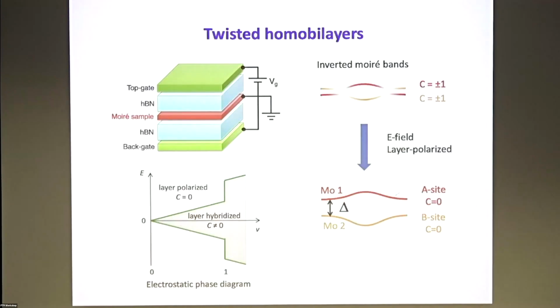So this is a typical device structure that we look at. Sometimes a bit more complicated, but this is sort of the idea. This is the twisted bilayer sample sandwiched between boron nitride, which is a very good gate dielectric. And then the top and the bottom are usually graphite gates, pure few-layer graphite gates. And because we have two gates here, we can tune independently the density of electrons in the system, as well as the vertical displacement field through the bilayer. And because the vertical displacement field can also tune the topology of the bands, this is a kind of phase diagram that you can try to remember.